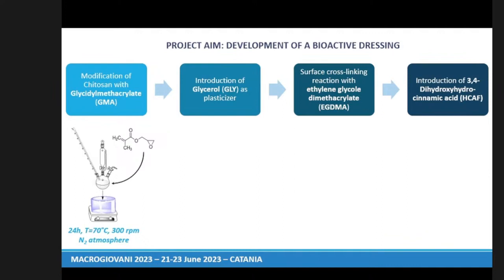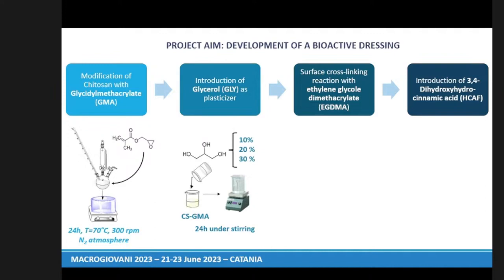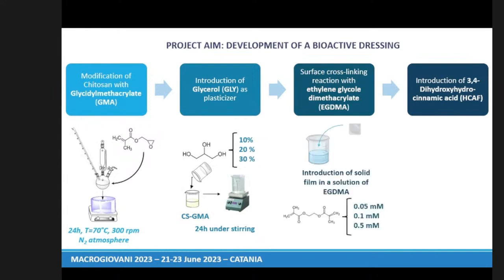In the second phase, we decided to introduce glycerol, named GLY, as plasticizer at 3 different concentrations in order to see how this can modify the mechanical properties of our matrix. And as I said before, our matrix has to be cross-linked, and for this reason we decided to use ethylene glycol dimethacrylate, named EGDMA.